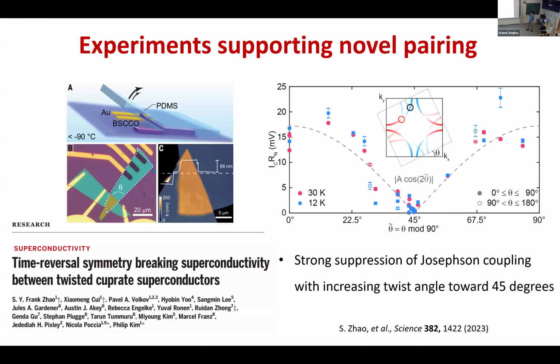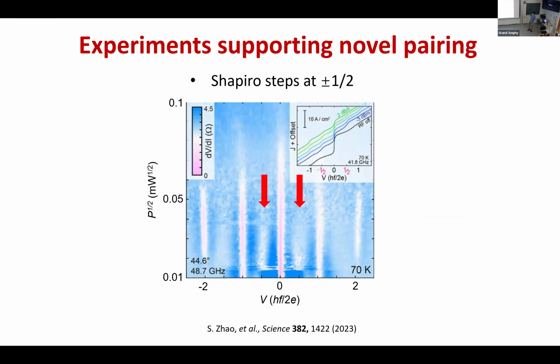So Shapiro steps also. This is the experiment of Philip Kim's group at Harvard. They are claiming time reversal symmetry breaking superconductivity when they do this twist. First of all, they observe a very strong suppression of the Josephson coupling when you go from 0 to 45 degrees, which is different from our observation. We don't see such a large suppression. But still, around 45, they do see some coupling, and they claim this coupling is coming from this d+id. Because of this d+id, they observe Shapiro steps between the integer numbers. These are Shapiro steps at 1/2 and −1/2. Also here something at 3/2. So with these features, they say this is consistent with the expectation that we have charge 4e. So it changes your hf over 2e to hf over 4e.